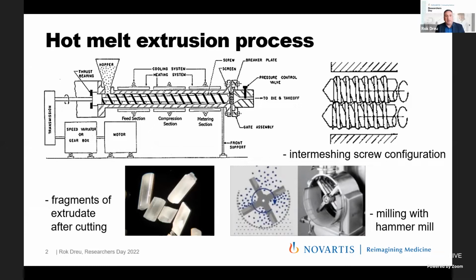Formation of drug-solid dispersions in a polymer matrix is an important approach to solubilize and improve dissolution rate of poorly soluble drugs that would otherwise lead to poor or insufficient drug bioavailability. Hot melt extrusion is a suitable technique that, by means of shearing material via 2 or more screws, introduces enough mechanical energy to soften polymer matrix and facilitate the formation of drug-solid dispersion. Solid dispersions in a form of cylindrical extrudates are then usually milled and filled into capsules or pressed into tablets.